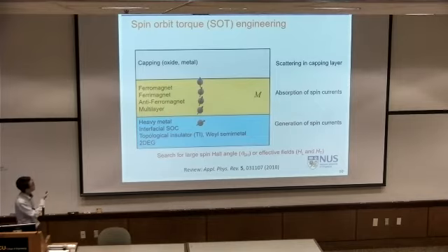Then the capping was largely ignored. And typically people thought, we have this two-functional bilayer, but if you change your capping, oxide or metal, you will change the whole electric field in your structure. So if you change the electric field in your whole structure, what will happen? The Rashba coefficient will change because you have a different effective magnetic field experienced by electrons.